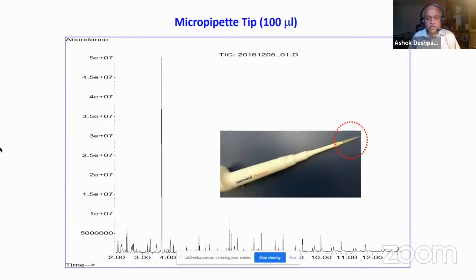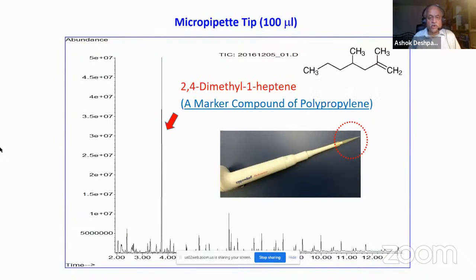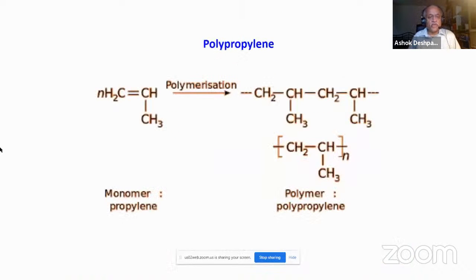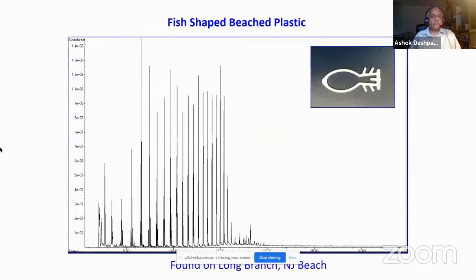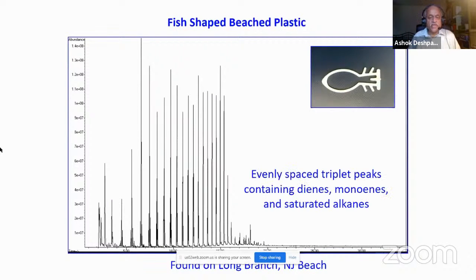So this micropipette tip, which is commonly used in the laboratory, has a marker peak of polypropylene. When propylene molecules polymerize, it forms polypropylene. This plastic piece has evenly spaced triplet peaks, which contain dienes, monoenes, and saturated alkanes. It is a signature of polyethylene.